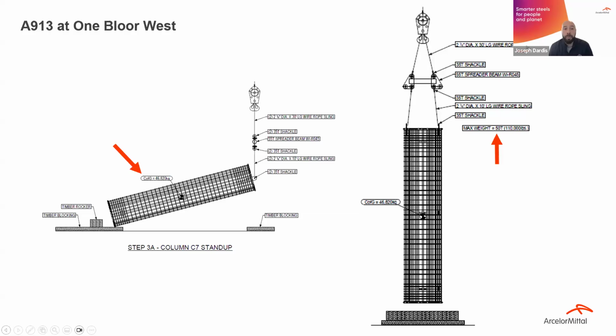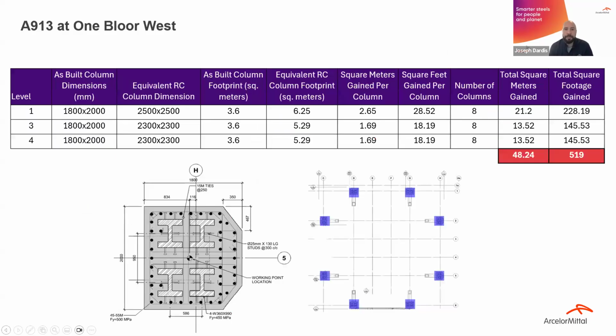So this is where A913 was really critical, because if conventional 50 KSI steel was used inside those mega columns, you would have been way north of that 50-ton max crane capacity. So yes, it saved weight and that saved money on the material, but you also saved a lot on not having to splice a column that looks like this, which I can't even fathom what that splice would look like. But it would have been an extremely labor-intensive and an expensive process, or having to bring in a different size crane with a much higher capacity. So these are some of the hidden benefits that aren't necessarily obvious at the onset. Yes, there was a weight reduction, but there's also these constructability advantages that we don't necessarily see right from the jump. And we can look at the next slide too.